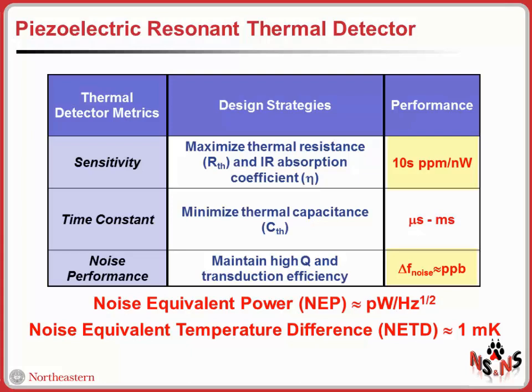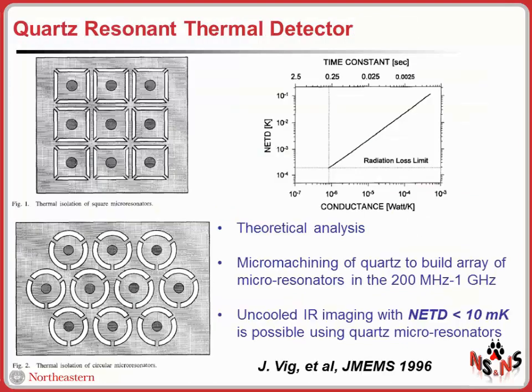So in other words, what is really crucial for the development of this piezoelectric resonant thermal detector is the scaling of these micromechanical elements, which really enables the capability to achieve high thermal isolation and low thermal mass. This idea was proposed about 20 years ago by J. Vig, who demonstrated theoretically that by micromachining of quartz, it would be possible to build microresonators operating in the 200 megahertz to 1 gigahertz range that can be made very highly isolated from the heat sink, and therefore could be used as very good thermal detectors. In fact, he demonstrated that using this approach, maintaining the high quality factor of quartz resonators, it would be possible to achieve a noise equivalent temperature difference in the order of 10 millikelvin, which is of course quite good for infrared sensors.